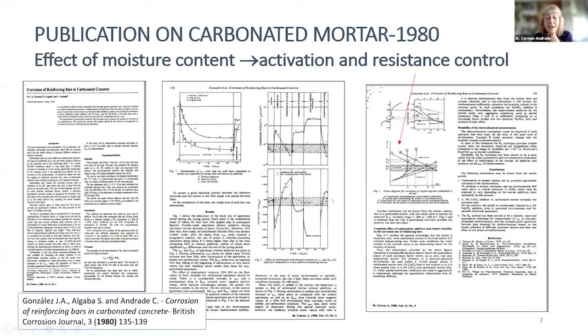At that time, I was starting to apply this to concrete or mortar specimens, changing the amount of water, because aqueous corrosion needs water. In that case, the water was the variable, and we realized that there are big changes when we go to 100% relative humidity or partial immersion, and when we dry, the corrosion rate is smaller, and the same happens with the potential.